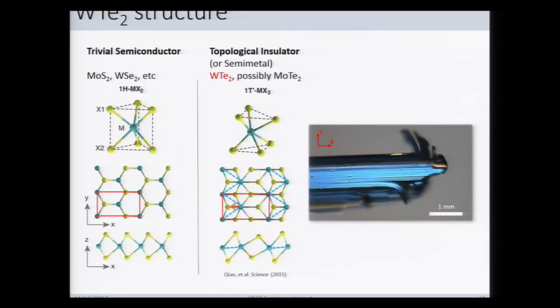And this is an actual crystal that we've received from our collaborators, Bob Cava, where you can see, this is sort of a side view, and you can see very clearly that it has a layered structure and it's already sort of peeling away from itself like the pages of a book. And this is very nice because you have this nice big crystal, the scale bar is a millimeter here, that you can work with for exfoliation, and it's very likely that it will exfoliate, and indeed it does.